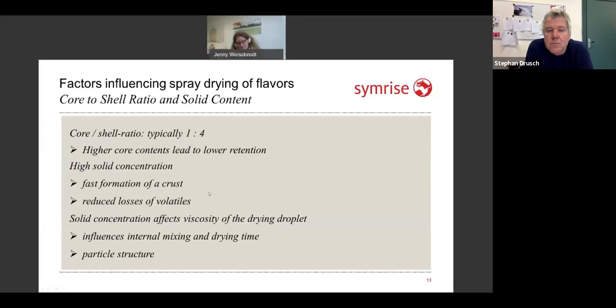But on the other side, your solid concentration affects the viscosity of the drying droplet. If it's not too high, it will prevent too high internal mixing and movement within your droplet, and it will keep your volatiles inside. If it is very high, it will increase your drying time, and this can, in this case, lead to a higher loss of your components, and it will directly influence the particle structure.